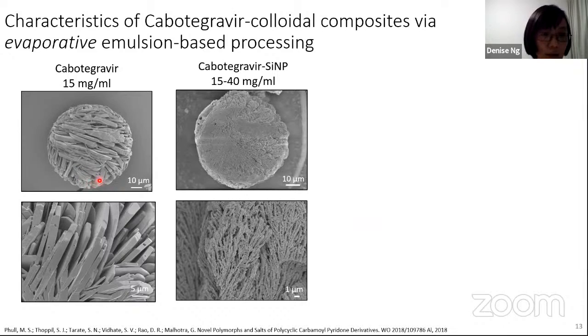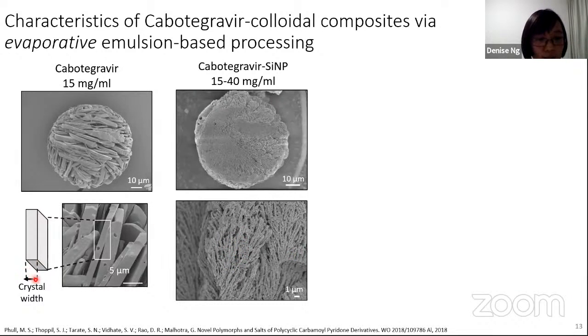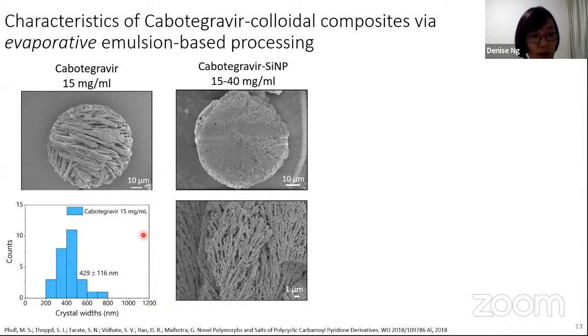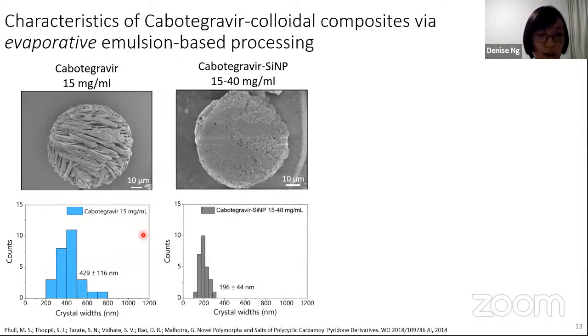So in the case of both the neat case as well as the composite case, we observe that both of them form nice spherical particles. In particular, with the neat case, we observe that it forms large lath-like crystals, whereas in the case of the composite, we see that it forms very thin lath-like crystals. And we also quantified the changes in terms of the crystal width. Here, in the case of cabotegravir, we observed that it forms a distribution of 429 nanometers plus or minus 116. But in the presence of colloidal silica, we see a significant narrowing and a significant decrease in the crystal width size.